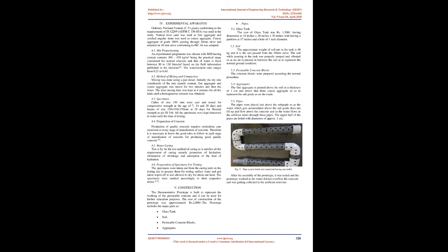4.1 Mix proportioning. An experimental program was chosen with M20 having cement contents 300 to 450 kg/m3, being the practical range considered for normal concrete, and that of water is fixed between 90 to 130 liters/m3 based on the field information published in the literature. The water/cement ratio ranges from 0.21 to 0.43.